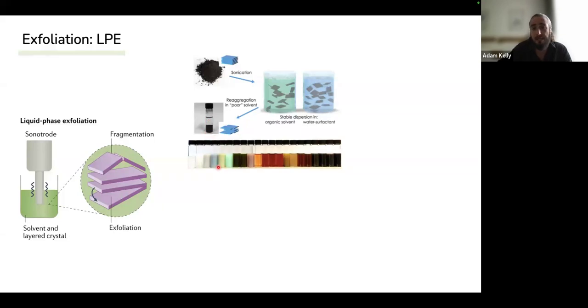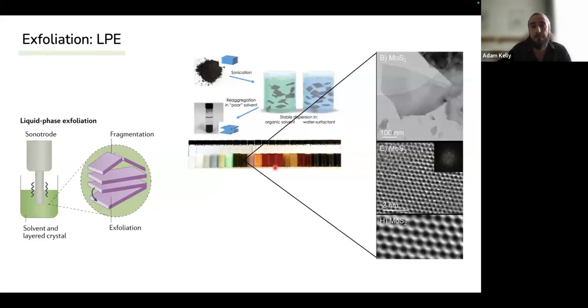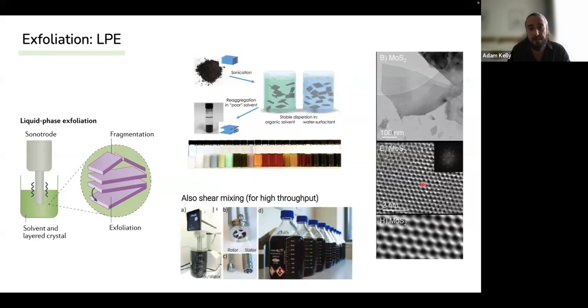Now, the beauty of this technique is that it works for pretty much any material you can think of. There's no electrical limitations on this. And when we apply this process to any of these crystals and look inside, what we find are nanosheets. And what's important to note as well is that when we look at the basal planes, for example, of these exfoliated nanosheets, we find that they're generally quite pristine. So it doesn't induce any damage into the basal plane itself.